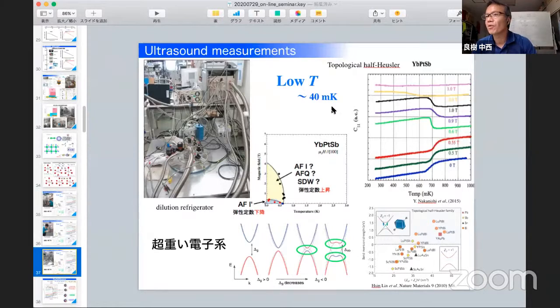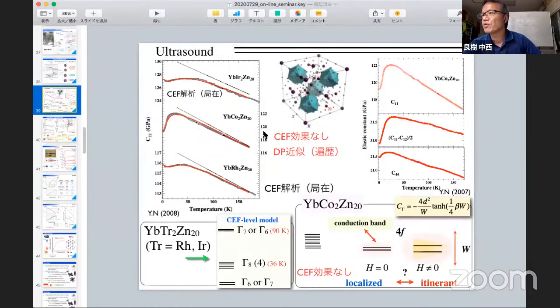Okay, so skip. And I'd like to show you another ytterbium compound system. This is the so-called ytterbium 2-20 system. They also show elastic softening, as shown here in the temperature dependence of the elastic constant. In particular, in the case of ytterbium cobalt 2 zinc 20, we have a pronounced elastic softening characteristic behavior at low temperature like this.